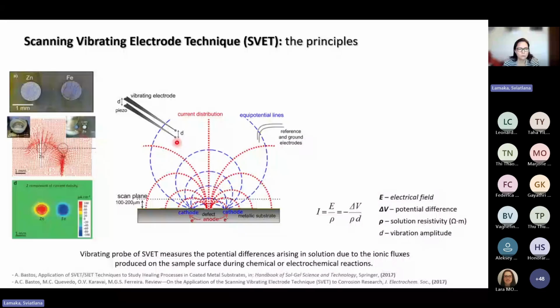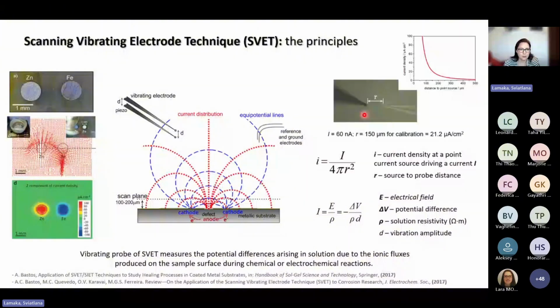This is done based on this equation: if we drive 60 nanoampere current at this distance, we expect to reach 21.2 microamp per square centimeter current density. So basically, SVET registers outbreaks and suppression of local corrosion.